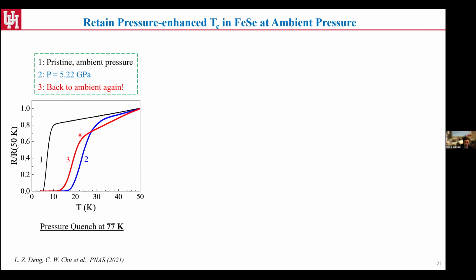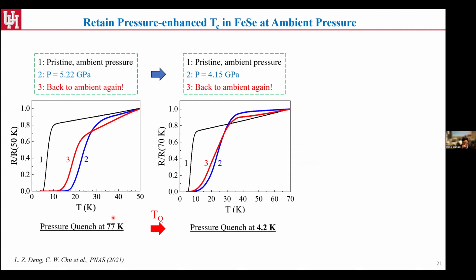So we are thinking, what can we tune further, right? So here, one key parameter, as I mentioned earlier, is the quenching temperature. So in order to reduce the thermal barrier, we're trying to go even lower, to 4.2 Kelvin. So imagine at 4.2 Kelvin things are more stable, and we don't have to overcome those thermal barriers. So that could give us a larger chance to lock in the high TC phase. Actually, that's exactly what we observed later.